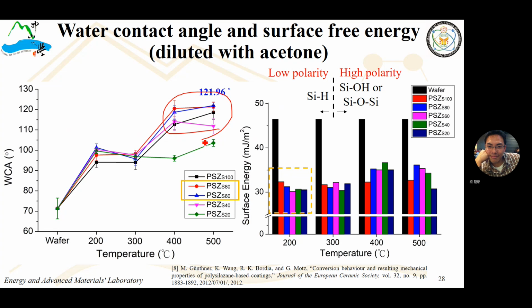122 degrees. Oh, I forgot to mention that for hydrophobicity, if the contact angle is less than 90, that means the surface is hydrophilic. And when the contact angle is higher than 90 degrees, that means the surface is hydrophobic. Of course, there are different criteria. Some will say when the contact angle is higher than 120 it is called super hydrophobic, and some will say it has to be higher than 150 degrees. Here, the contact angle has to be higher than 120 degrees for its hydrophobicity to belong to super hydrophobicity.